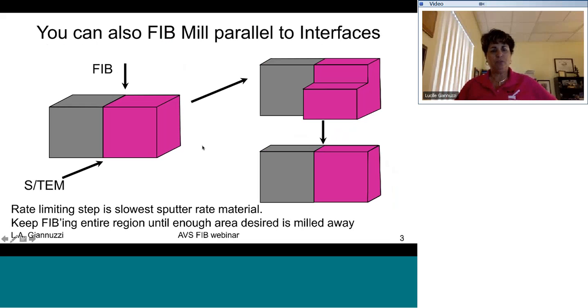It is also possible, of course, to FIB mill parallel to interfaces. If you're FIB milling parallel to interfaces, you have to remember that one side of the sample is probably going to FIB mill at a different rate than the other side. You can also possibly get certain artifacts, so you have to be careful there. But your rate limiting step there in achieving the depth that you want is going to be the slower milling material. Okay.